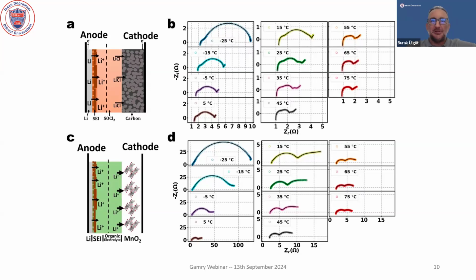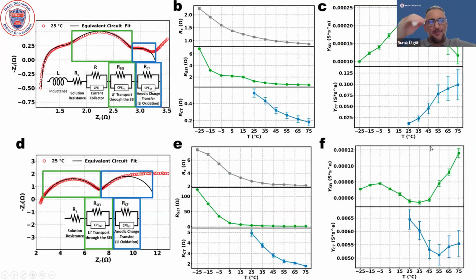This is not like infrared spectroscopy where you can say a peak at 1600 wave numbers belongs to some CO double bond. Impedance spectroscopy requires understanding of these processes because timescale is the only knob we have, and it is not chemical specific. Okay, so we can take those resistances, plot them versus temperature, understand their behavior. Some of them behave exponentially, some of them behave linearly, and we can use that information to not only identify the proper process, but also understand that process, like getting activation energies or conductivity coefficients.